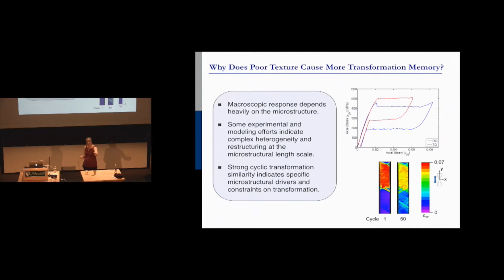And what we think is happening is that the first time you transform, you lay down a dislocation network, you lay down martensite variants that get locked in, and it's almost like a net of things that don't change, and then you have to work within that net, and so you get similarity that happens. But we really wanted to see what was going on at the microstructural level.